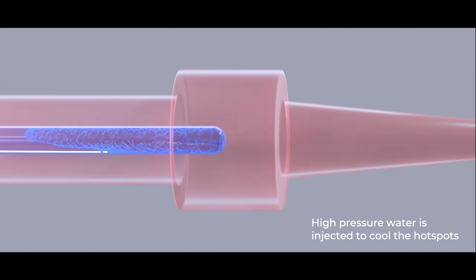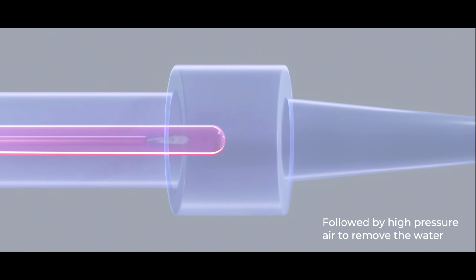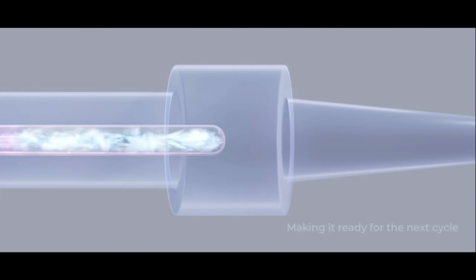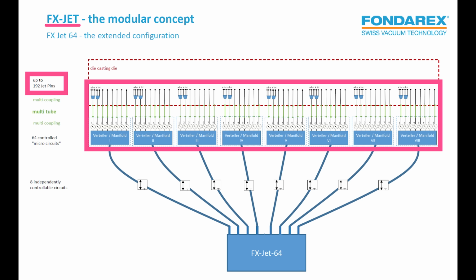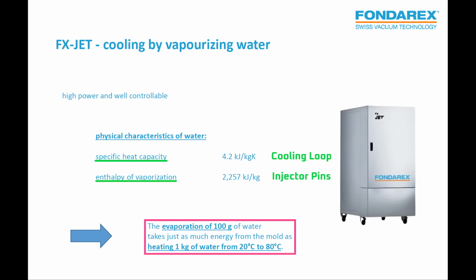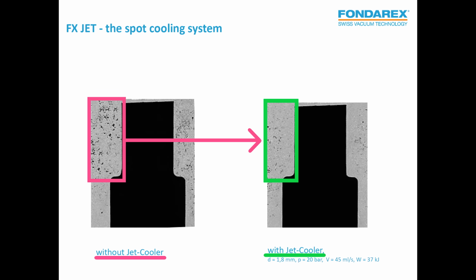FX Jet helps with those issues by providing greater control of the cooling process by using evaporative cooling injector pins throughout the die, up to 192 of them. And the temperature and timing of each of those pins can be strictly controlled so that every part of the casting cools at the ideal rate and at the right moment. Additionally, using evaporative cooling injector pins is a far more effective cooling strategy because vaporizing the water draws heat energy from the die much more quickly than a coolant loop does. As you can see on screen, the result of FX Jet is a significant reduction in porosity, which leads to fewer defective parts and parts that have more consistent strength and ductility.